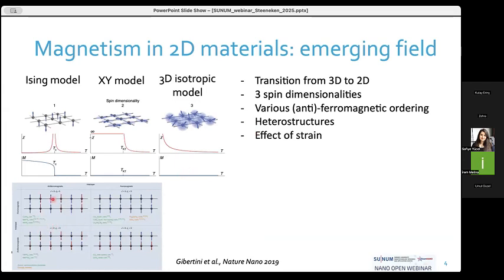This figure explains a little bit more the different types of ferromagnetic and antiferromagnetic ordering that can occur. If you have 2 layers of 2D materials, which are each 1 atom thick, and you stack them on top of each other, you can have a situation where all the spins are pointing in the same direction. This is the ferromagnetic ordering case. However, you can also have cases where the spins are pointing anti-parallel. And there are 3 types of ordering, and actually 2D materials have been found that exhibit all those 3 different types of antiferromagnetism.